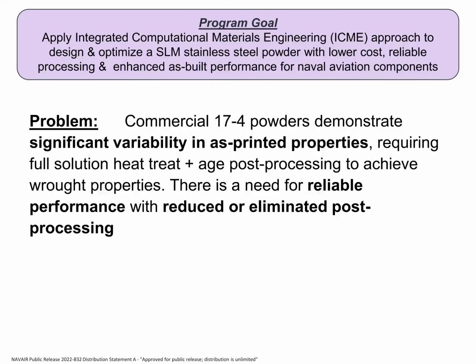At the beginning of this program, QuesTek was challenged with the need to create a 17-4 material alloy for 3D printing that was reliable in performance and also reduced or eliminated the post-processing requirements. QuesTek applied our ICME approach and interrogated ways in which we could look at the processing as well as minor changes in chemistry that would allow us to print in a process parameter set that achieved the ability to self-anneal and self-age the 17-4 as it was printed, thus allowing for an alloy that required very little post-heat treatment.